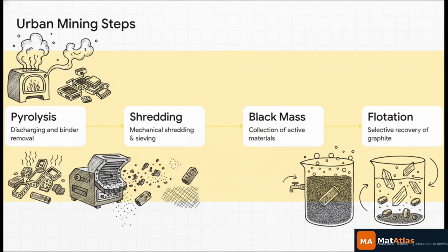From this black mass, we use clever techniques like froth flotation to jointly recover battery-grade graphite, which is actually 15 to 20% of a battery's weight, alongside the lithium metal oxides. And fascinatingly, studies show we can recirculate the process water up to 3 times without impacting the recovery grade, making this a highly water-efficient process.